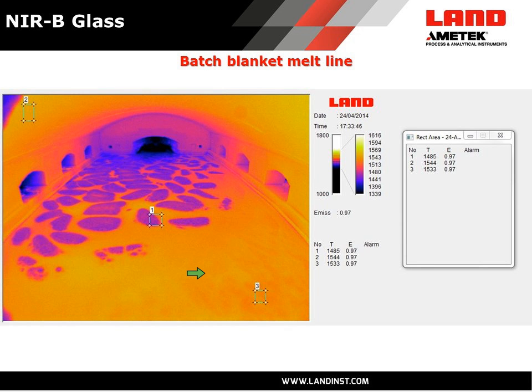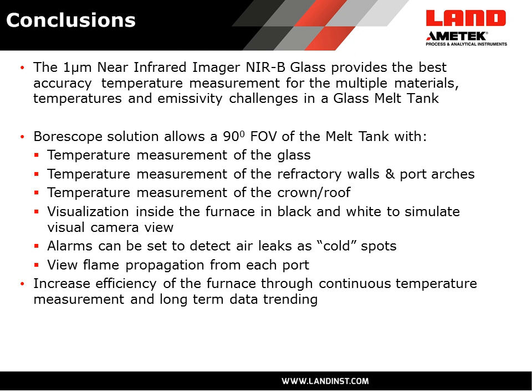The customer was, in this particular case, also interested in not just crown temperatures, but also the temperature of the melt itself, and also visualizing where that melt line occurred, so that the glass was fully homogeneous by a certain point. So this 1 micrometer, very short wavelength, near-infrared thermal imager provides very high accuracy temperature measurements for the different materials you find within a glass melt tank, whether it's the glass itself or the unmelted batch or the refractory brickwork within the tank itself.